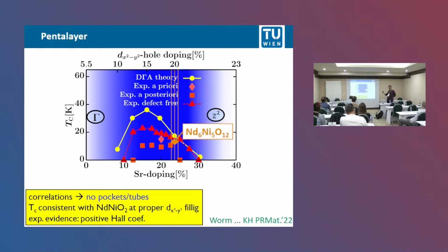And that is, of course, clear if you have no pockets, no electron pockets, you only have the Hall-like x squared minus y squared orbital, and that gives rise to a positive Hall coefficient. Whereas for the infinite layer compound with the pockets, at small doping, you have negative Hall coefficients, which one would also expect from the theoretical calculation.